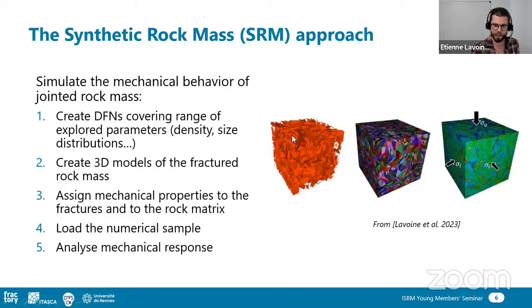rock mass. And then once we have these fractures, we need to create a 3D model of the fractured rock mass. So we have the domain that is cut by the fractures into different blocks that are stuck together, and we assign mechanical properties to the fractures and to the rock matrix. And then we perform numerical simulation of loading. So this is a test, just like in the presentation before, but this time this is done numerically. And we can just after analyze the mechanical response, such as the macroscopic behavior, macroscopic stress and strain, but also what happens inside. So you are able to access the stress at every point of the model. So you are able, for example, like in this study, to study the stress fluctuations associated with such a medium.